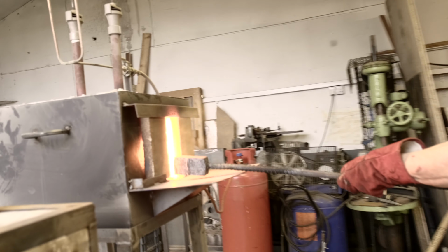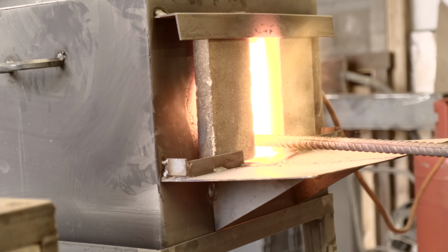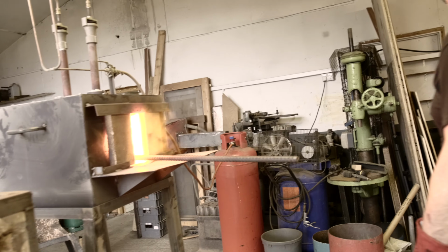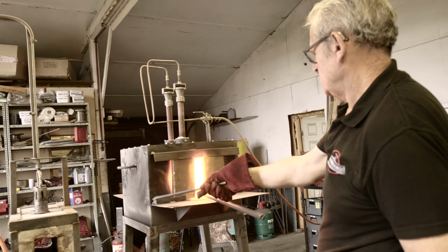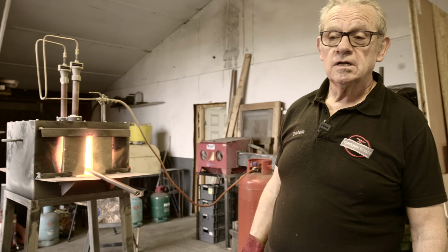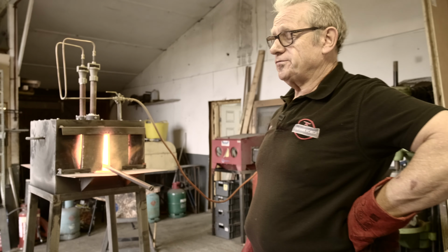There, we're nice and hot. Get him right into the middle of the hot zone. Close the doors up a little bit. That'll take 10 minutes or so, to let the heat soak right through to the middle.